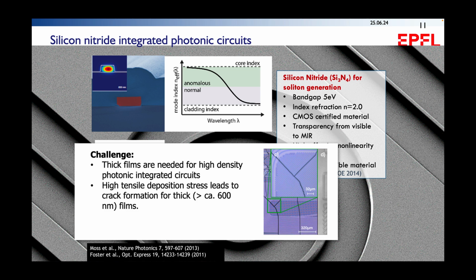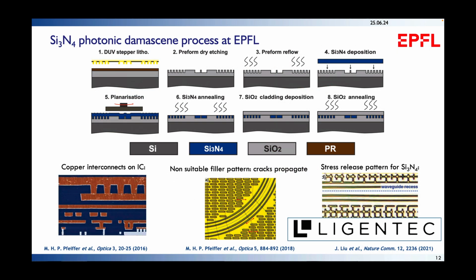While beneficial as a stressor layer, this is of course catastrophic in manufacturing integrated photonic circuits with low loss. The way you can overcome this is using two tricks. The first trick is that, instead of etching the silicon nitride, we take an oxidized silicon wafer and etch trenches, and these trenches serve as a stress release layer. The very high stress that builds up in the film relaxes due to the presence of the trenches. In addition to trenches, we also etch waveguides into the glass itself.